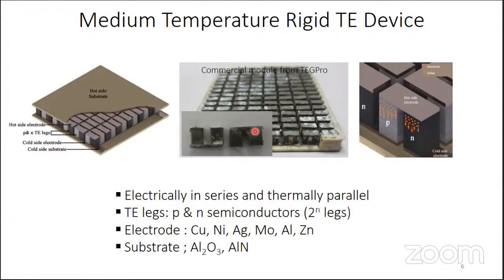So what matters is, in that condition, does this material have adequate thermophysical stability? It means it should not create any stress or cracking. Or thermochemical stability, in terms of diffusion of material from the electrode into this semiconductor material, or counter diffusion, or any sublimation of the material that is continuously exposed for several hours. There could be some sublimation, or if there is a little oxygen, some oxidation and degradation. It should be free of all these things to work continuously without degrading its performance. So that's very, very important.